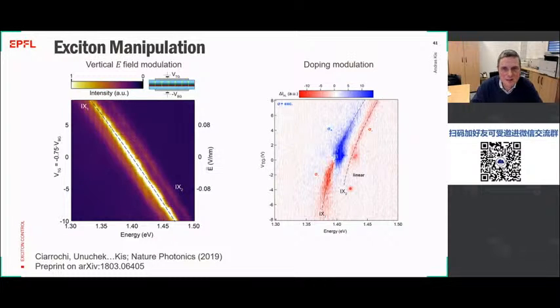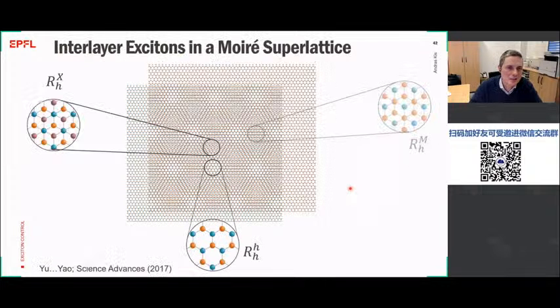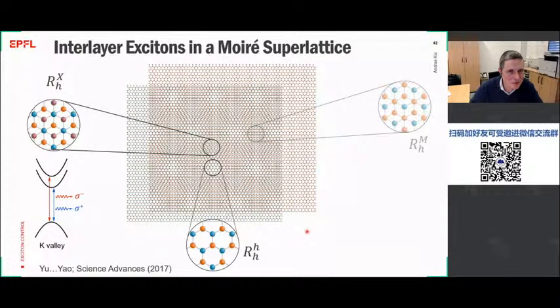So the way we explain these results is that, in this Moire superlattice between the two materials, Wang Yao from Hong Kong has predicted that we're going to have different types of selection rules depending on which region of the Moire lattice is optically active. So depending on the local symmetry, different portions of the Moire superlattice will have different selection rules. In the same valley, these two transitions will emit with different polarizations.